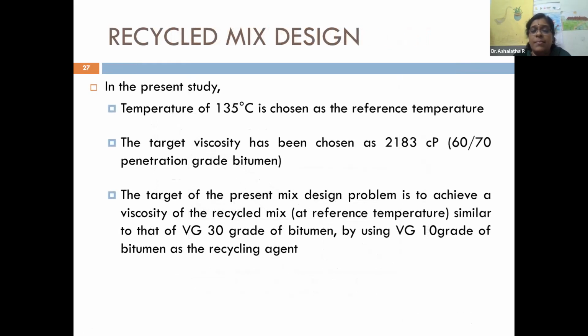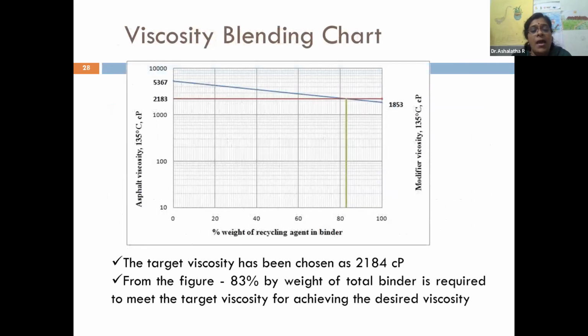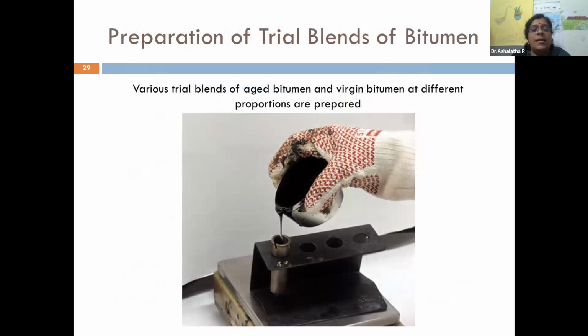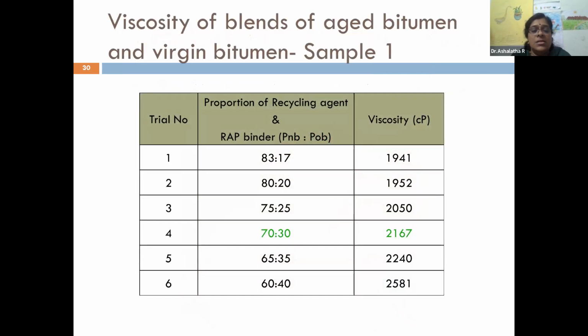In the present study, we used 135 degrees as the reference temperature, and the target viscosity was chosen as 2183 centipoise for VG30. The target of the present mix design problem, as I said, is to achieve a viscosity of the recycled mix at the reference temperature similar to that of VG30 grade bitumen, using VG10 grade bitumen as a recycling agent. So for this first sample, from this figure we got that 83% by weight of total binder is required to meet the target viscosity. Various trial blends of the aged bitumen and virgin bitumen at different proportions were prepared. This is the trial and error process, and finally we found that at the ratio 70:30, the proportion of recycling agent and RAP binder, it was almost closer to the target viscosity.